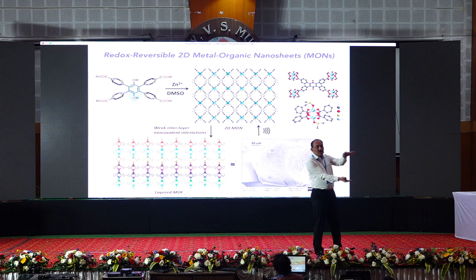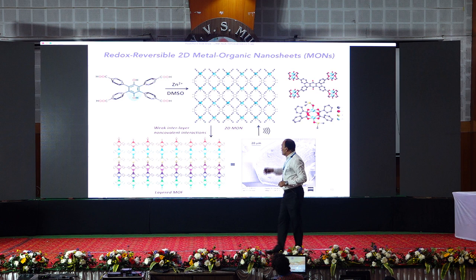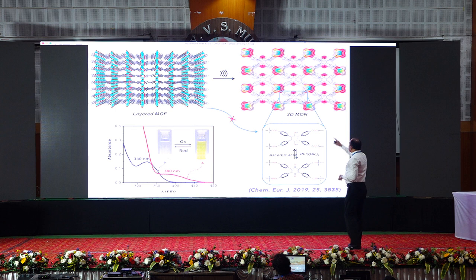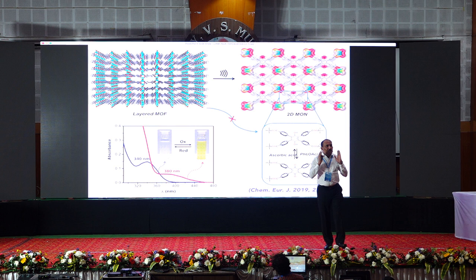And I told you, right, exfoliation can be done by ultrasonication. UILPE, ultrasonication induced liquid phase exfoliation. But you ought to have the 2D material. And you get to the 2D material, and of course that's how it macroscopically looks like. Now, if you look at the structure as determined by X-ray crystallography, you can see the porosity. Now, because I have the porosity, I can worry about even doing the chemistry on them.